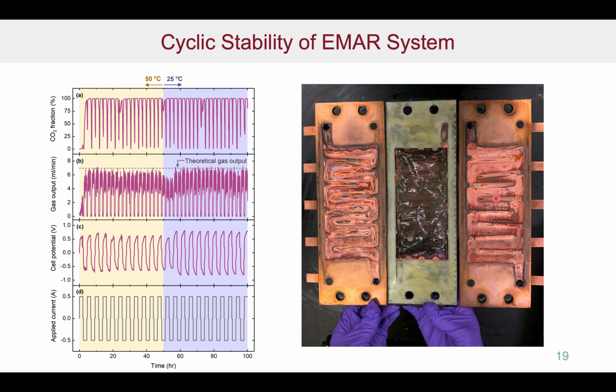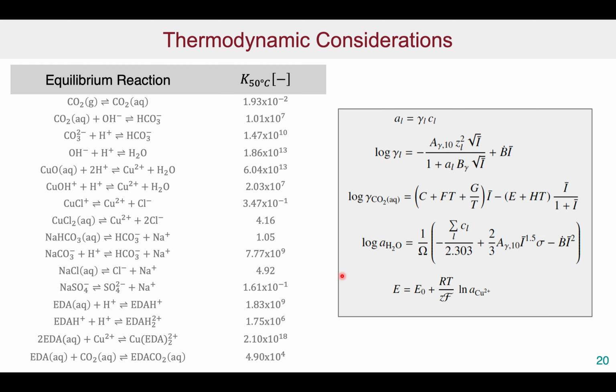You can see these electrodes look pretty good after 100 hours of operation. They still look very clean and just look like pure copper here. We don't get much contamination with other species on the electrodes.